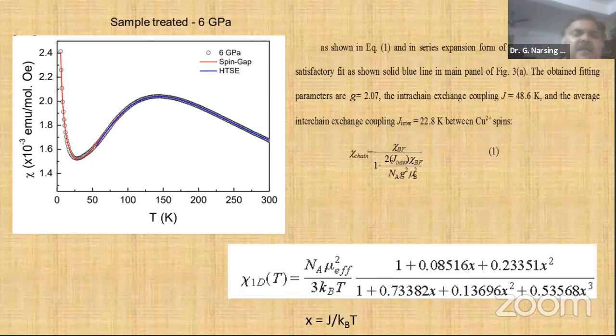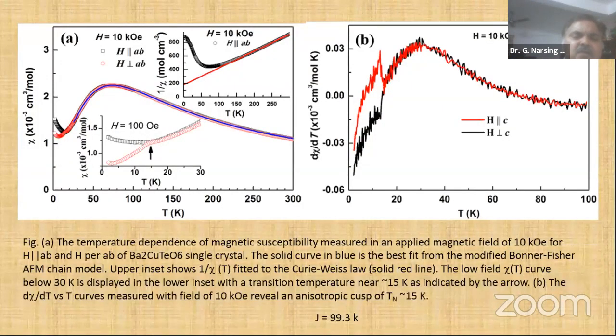So here we have a single crystal of the Ba2CuTeO6 triclinic one. You can see there are different directions: H parallel to AB, and H perpendicular to AB, meaning along the C-axis and parallel to the C-axis. If you make the surface a different way, the magnetic field will be in a different direction, so you will get a different type of magnetization. You can see here. Normally you might say there may be some experimental error, but we measured this type of sample so many times. Different crystals also we measured.